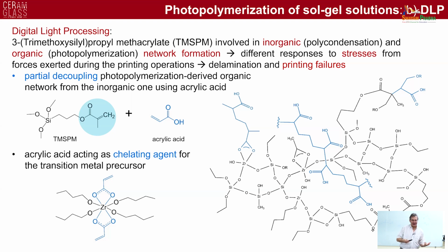And a gel doesn't have enough strength to withstand this lifting, and therefore we made sure that we were able to develop an organic photopolymerized network inside the system in order to provide enough strength to withstand the stresses from the forces exerted during the printing operation.